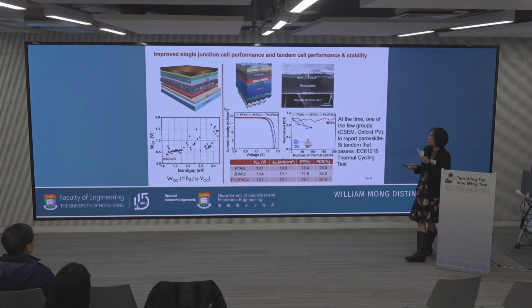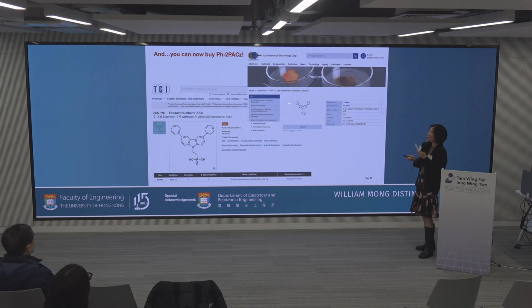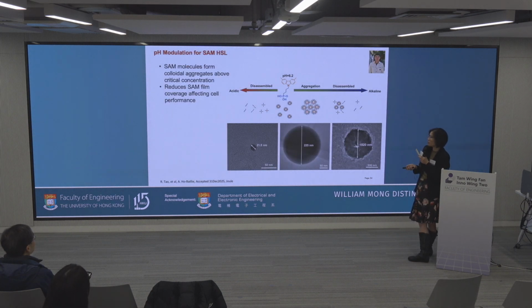high band gap material. And because it's thermally stable, we were able to get the cell to pass the IEC 61215 thermal cycling test. Okay, so the good thing is now you can buy this material. We didn't patent it, much to the disappointment of our university, but we feel like we're contributing a little bit to changing the world through renewable energy development. Okay, so I don't have a lot of time left, so I won't touch on this work because I would like to talk about stability.